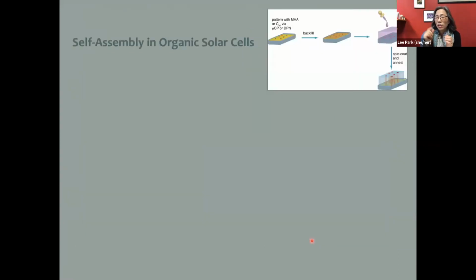So with that, I can tell you just a little bit about how this relates to work that I've done. I have done some work in the area of organic solar cells. And in some of that work, I used some of the techniques that I've already told you about. So in this slide, this is an illustration of chemically patterning a surface, which I did with different size patterns, both through microcontact printing, which made micron size patterns, as well as through dip pen nanolithography, which made nanometer size patterns. And then you can coat that surface with a polymer film, and you can let that polymer film anneal and look at the self-assembly that you get. And again, the goal of this project was really to try to impact the interior architecture in that polymer film in order to improve the efficiency of a solar cell. So that was one kind of work that I did some years ago.